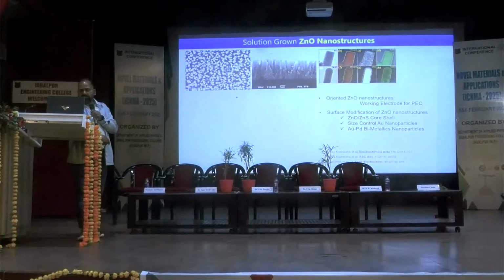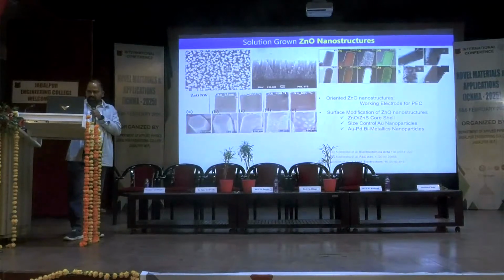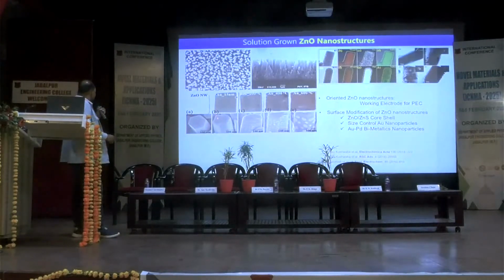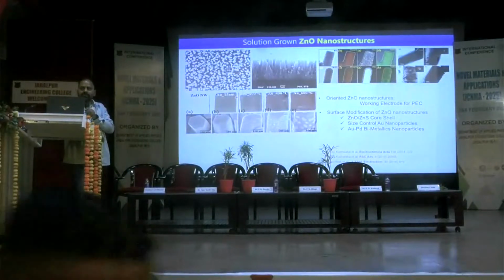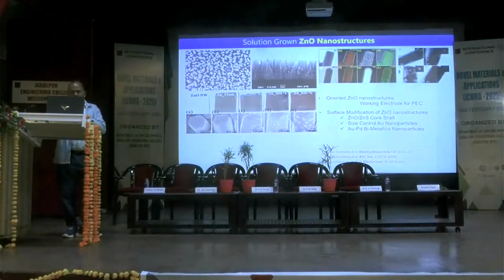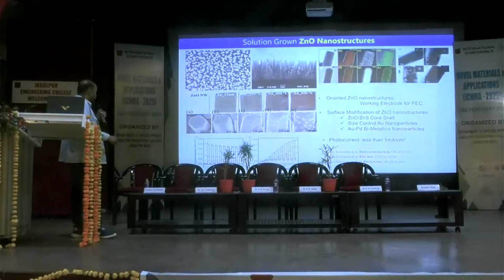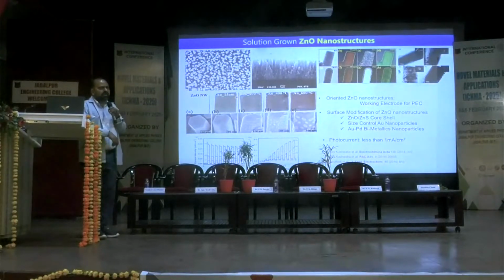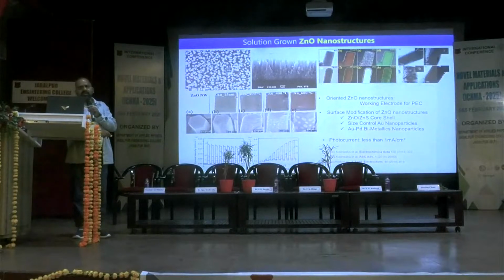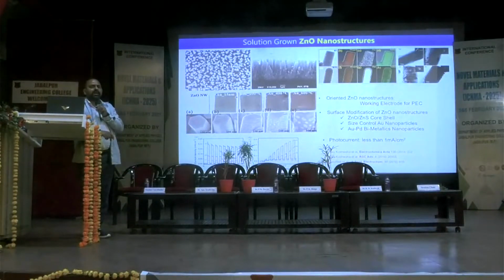Then with another approach, we modified this zinc oxide with size-controlled gold nanoparticles. I think you can see the images here. These different size gold nanoparticles are coated there, and we adopted a simple strategy. We coated 50 nanometer gold nanoparticles, and it had a very good impact on the photoelectrochemical performance. I'm not discussing all the detailed data, but after all these modifications, we only achieved roughly 1 milliampere per centimeter square current, which is still very less.